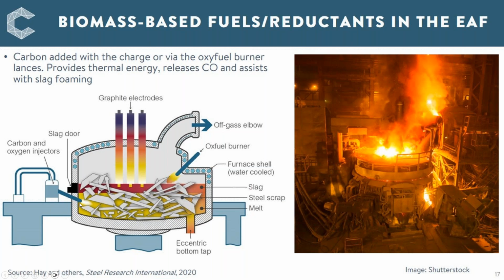And the injected carbon is important. It starts to form bubbles of CO2 and CO and so on as it burns, and that CO moves through the melted material and through the melted slag on top, and it starts to produce a foam within that slag. So the slag becomes a foam, and that protects the walls of the electric furnace and protects the electrodes as well. So a lot of the research on putting biomass in has been around this foaming behavior, and also obviously the chemistry that goes on in here to try and get the iron to the right level of carbon to produce steel.